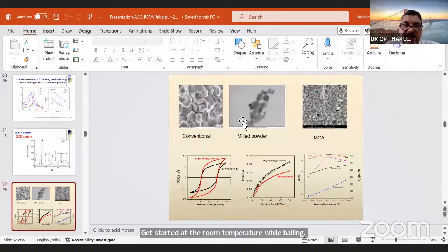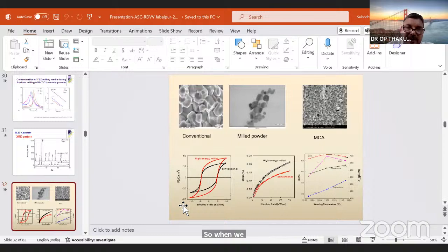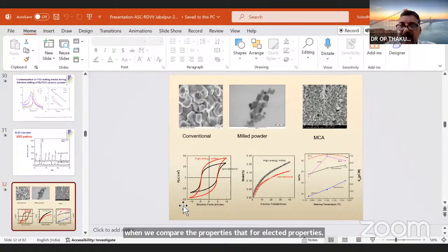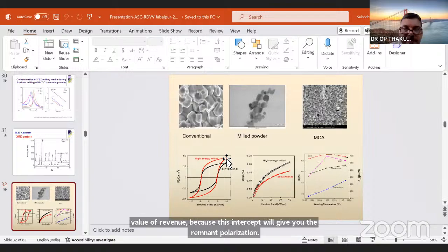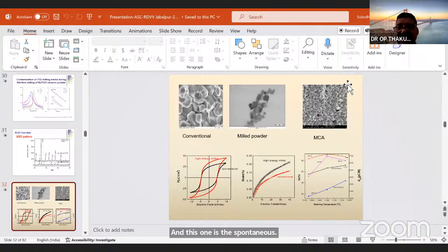So this is the grain size. I have taken a photograph using SEM. So in the conventional method, you can find the grain sizes are very large, but in high energy milling or planetary ball mill, you will get grain size that is very fine and uniform. So when we compare the ferroelectric properties for conventionally milled powder ceramic and high energy milled powder ceramics, what we found is, when we do the ferroelectric hysteresis loop, the value of remnant polarization, because this intercept will give you the remnant polarization, and this one is the spontaneous polarization. So the value of PR is increased because of this fine, uniform grain size distribution and high density.